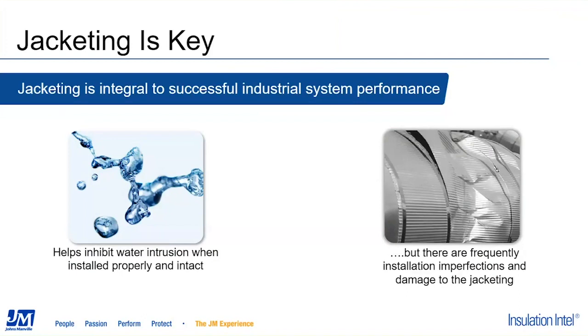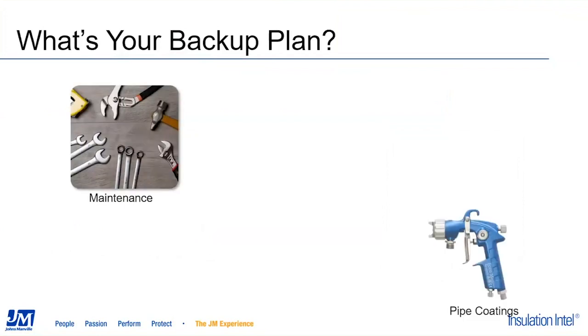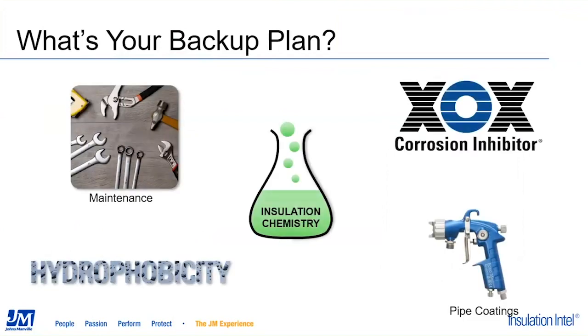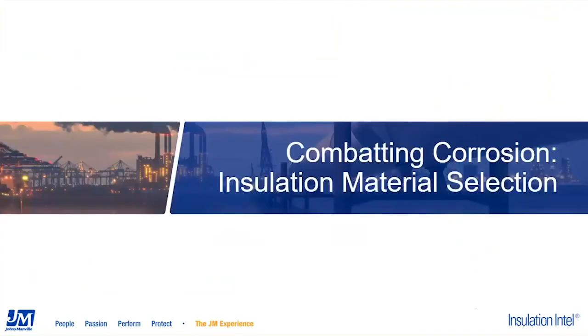However, if metal jacketing is damaged, not installed properly, or sealant failure occurs, additional lines of defense against CUI are necessary. Metal jacketing can reduce intrusion, however, water is inevitable. So you need a backup plan or additional lines of defense against CUI. Items to consider: coatings, pipe and tank with corrosion inhibiting coatings or gels, proper system maintenance, choosing proper insulation materials such as hydrophobic or XOX additives that help inhibit CUI. This brings us to the next section with Scott Sinclair to discuss combating corrosion and insulation materials.